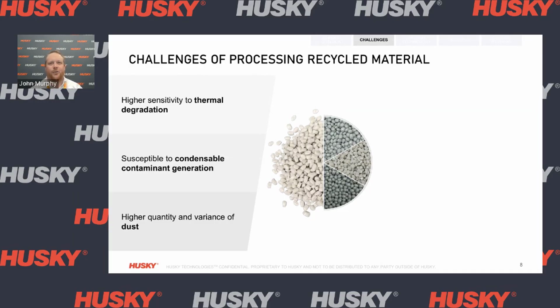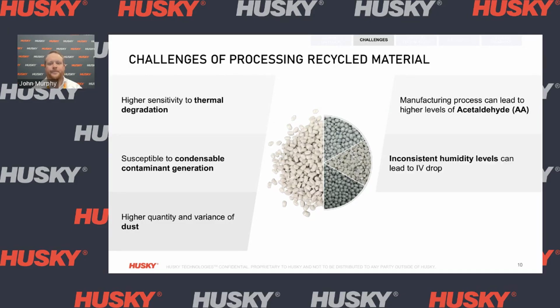Recycled material often includes a higher quantity and variance of dust that is generated during transportation. Dust can generate black spots on the preform, so this can cause significant issues with your final part quality. The manufacturing process of rPET material can also lead to higher levels of acetaldehyde, or AA, leading to an off taste in the final product. Because rPET can come with varying levels of water content, it can be challenging to dry to a consistent humidity level. This inconsistent humidity level can lead to IV drop that affects the performance of the final product. And lastly, the manufacturing process can lead to lower crystallinity levels. This can cause issues with bridging or sticking in the hopper if exposed to high levels of heat.